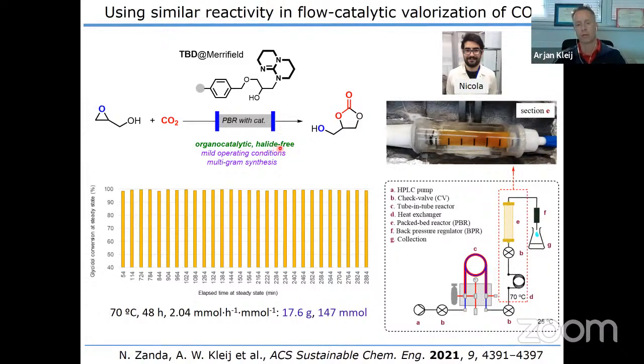and we can make that essentially halide-free under reasonably mild conditions, and we can make multi-gram scale synthesis of that compound under, I would say, extremely stable conditions. So when we take samples and we look at the overall conversion of the substrate, in almost all the cases, we see close to 100% conversion of the substrate.